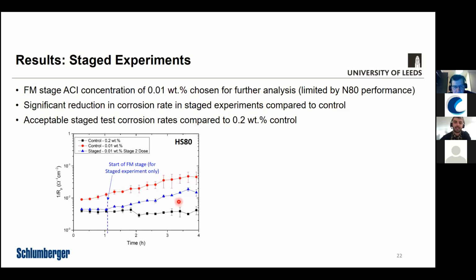And this slide compares the corrosion efficiency, essentially inhibition efficiency, of the staged approach. So this is just the blue line, when you compare the black line, which is the control at 0.2%, and the control at 0.01 weight percent. You can see there's a dramatic increase in efficiency of the inhibitor compared to the 0.01% control test, showing that, again, by performing that film in the initial stage, the lower concentration could still maintain good inhibition efficiency. And the values that we've reached at this stage are within acceptable values for what Schlumberger would deem as acceptable corrosion inhibition efficiency in this particular environment.